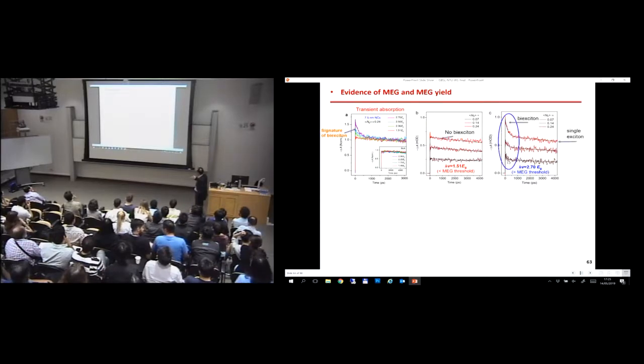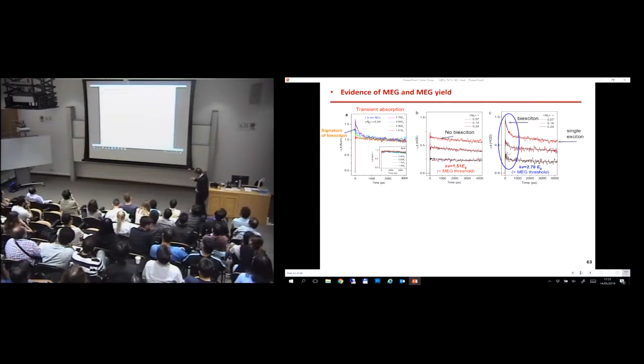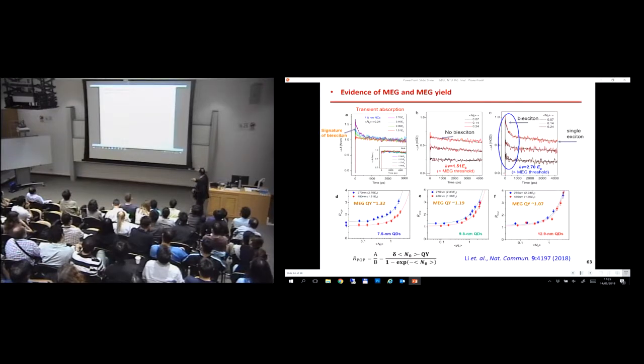So the signature comes from this bi-exciton signature, which is a very fast decay of the photo-bleaching signal, performed at very low pump fluence, 0.07 average electron-hole pairs inside the dot. This gives you very clear evidence that multiple exciton generation is actually occurring, with the formation of this bi-exciton. Now we can go on to determine the MEG quantum yield by taking the amplitude ratio of the bi-exciton to that of the single exciton. In the case of the smallest dots, it gives us a quantum yield of about 1.3.